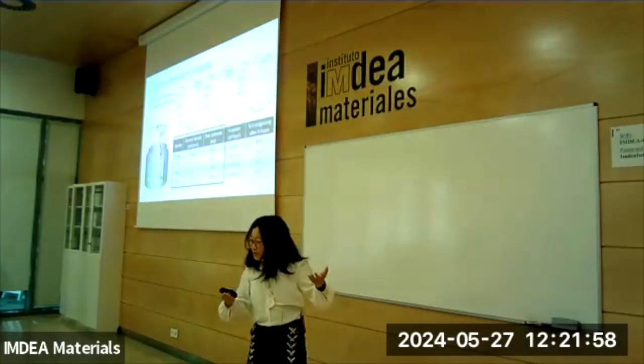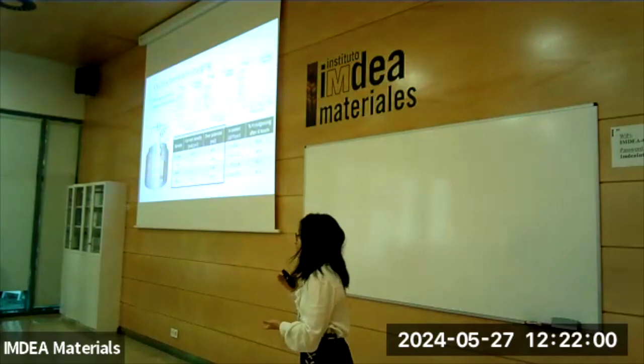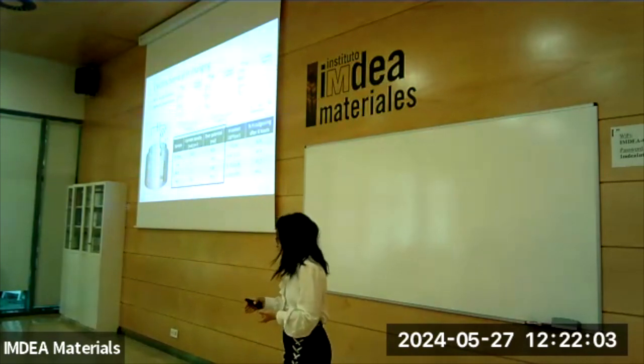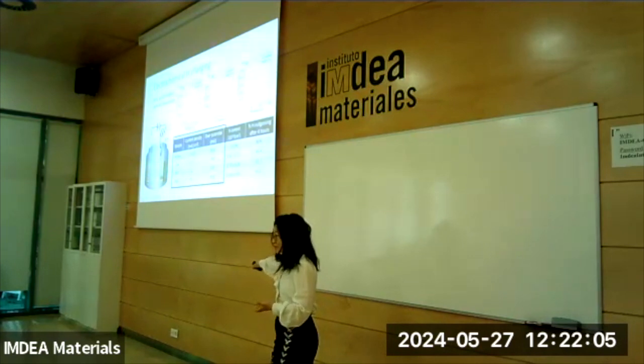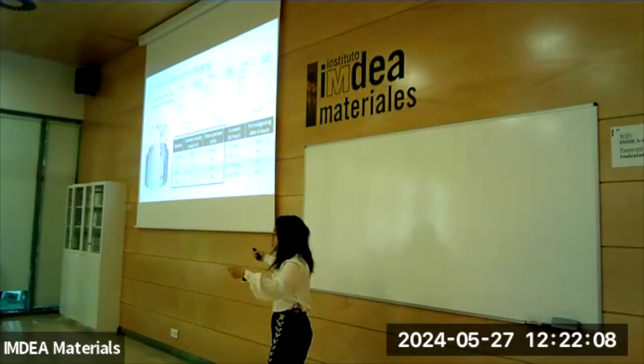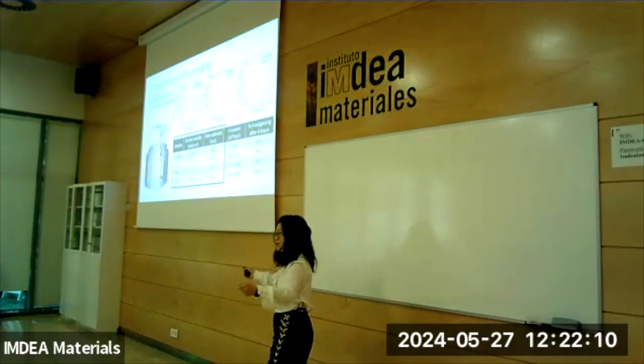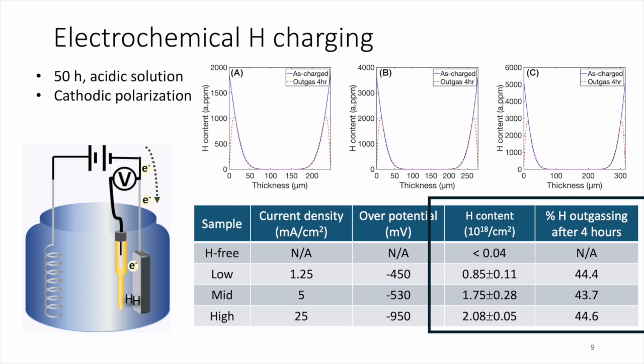Remember, what is our purpose? We want to see crack initiation. If we charge it through, the sample is going to be fully embrittled, and once we do the tensile test, what's going to happen? It's going to break. Nothing will be captured. Right? So with the surface embrittlement, we can capture many crack initiation events. It takes 4 hours from the moment we take the sample out of this electrochemical cell to the end of the tensile test. So then we also calculate the hydrogen outgassing after 4 hours, and we lose about 44% of hydrogen.